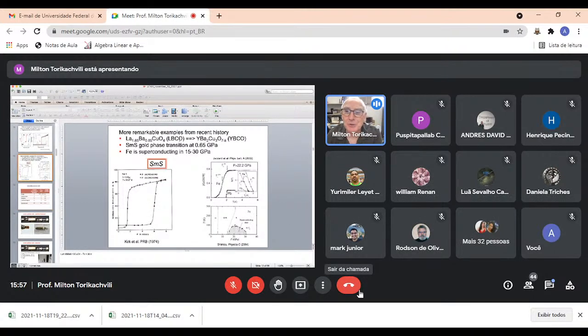Oh, and it's important to mention, we talked about chemical substitution before. See, in 1986, people manufactured lanthanum barium copper oxide, which had a record high superconducting transition temperature of 38 Kelvin. But then this man, Paul Chu, who was a pressure specialist, realized, well, lanthanum and yttrium are chemically identical or almost identical, but yttrium is much smaller. So what will happen if I substitute yttrium for lanthanum? So he did, and the superconducting transition temperature started going up, just as he did by applying pure pressure.